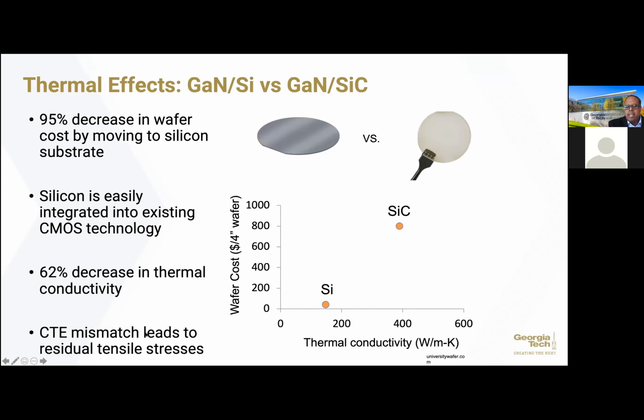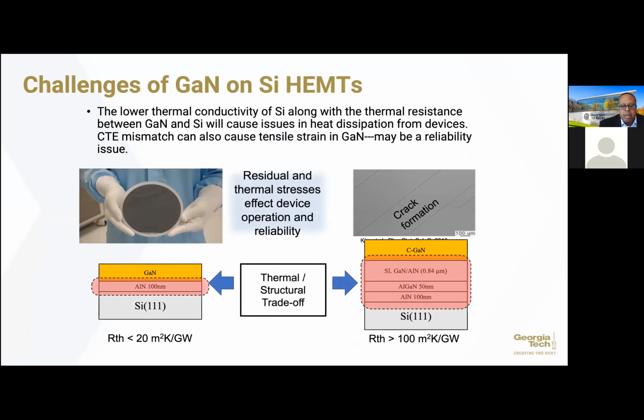And then we also know that there's a CTE mismatch between gallium nitride and silicon that leads to very large residual tensile stresses. And so it's not so simple to just take gallium nitride and grow it directly onto silicon, because it's not the same crystal structure, the CTE mismatch, other things that come into play. So what's typically done in the industry in order to control this, or in order to grow this, you basically take 111 silicon, you have to put this inner layer here again, just like I showed you before, between GaN and silicon carbide. So this is aluminum nitride that can be grown here, and then you can grow electronic grade gallium nitride on top. What we have seen in some of our measurements is that the thermal resistance of these inner layers here, when you have this structure, is on the order of 20 meters square K per gigawatt or less. So it's actually pretty good.